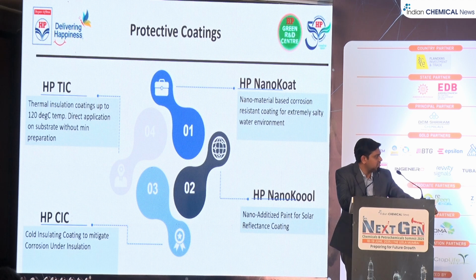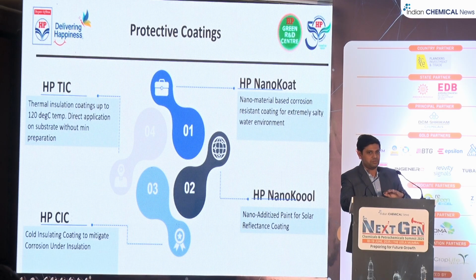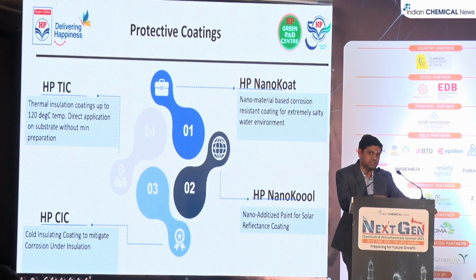Then there are HP CIC and TIC. These are basically our cold insulation coating and thermal insulation coating. Generally, in insulation there are 3 layers. One is the corrosion resistant coating, then comes some foaming, and above that the aluminum cladding. This coating removes the requirement of all these. You can directly apply this coating over the pipe.